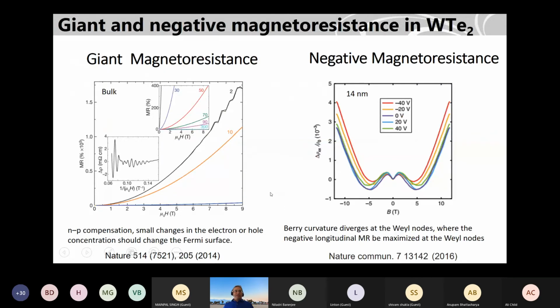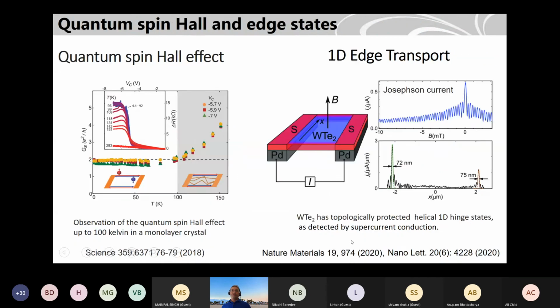I'll quickly go through some literature on what people have measured in this tungsten telluride. It shows a very giant magnetoresistance, up to 10 to the power 5 times in bulk samples, because it's a semi-metal. People saw some negative magnetoresistance at some angles, and that gives a chiral anomaly type of behavior.